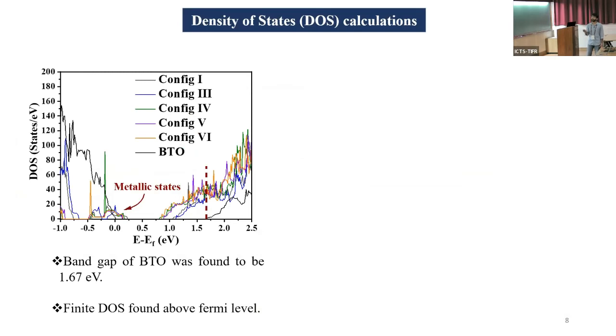set out to find the band gap of the system. For that, we calculated the density of states. For pure barium titanate, the band gap was found to be 1.67 eV, and the insulating band gap is shown by the vertical line in brown color. But for all the configurations we studied, we found metallicity, with finite density of states above the Fermi level, showing metallicity in the system.